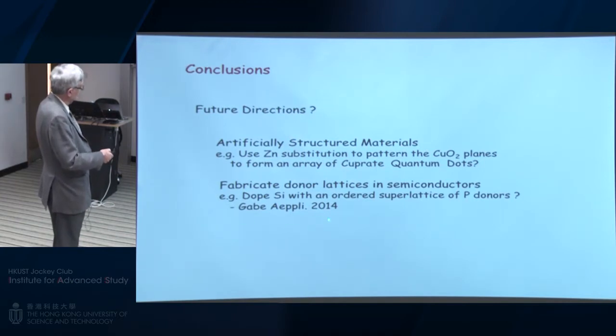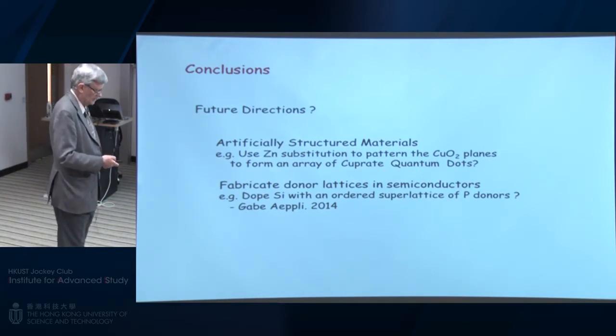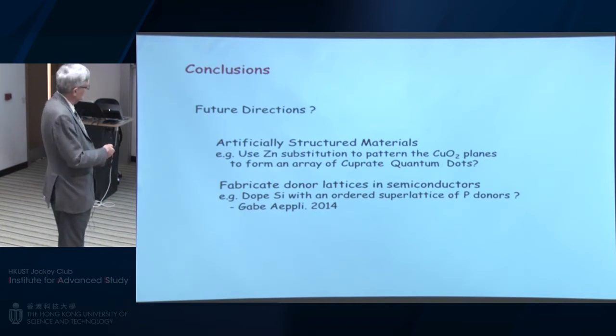Or another idea that I got from Gabe Aeppli, who's now moved recently to Switzerland, is to fabricate donor lattices in semiconductors. For example, the phosphorus dopant in silicon looks like a renormalized hydrogen atom. So if you could organize a superlattice of these donors, and you could change the lattice parameter, etc., maybe you could get some material which on the one hand had superconducting properties and on the other hand could be mapped in with the semiconductors. So there are interesting ideas around.